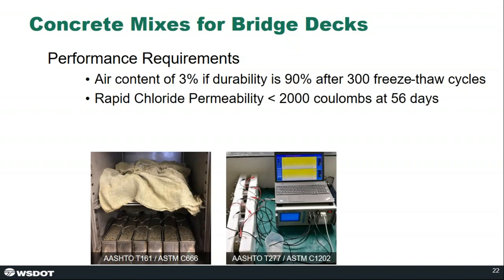We require a rapid chloride permeability test to demonstrate that the concrete has a permeability of less than 2,000 coulombs at 56 days. This is an accelerated test to pass charge through the concrete subjected to a voltage difference, and it's a measure of how permeable the concrete is to chlorides. Now, chloride ions generally move slowly over the course of years, and it's hard to qualify a mix on that sort of time frame. So this is a useful test to gauge permeability in a much shorter period of time. And so we've established a limit of 2,000 coulombs, which is generally consistent with an upper bound of low permeability concrete.